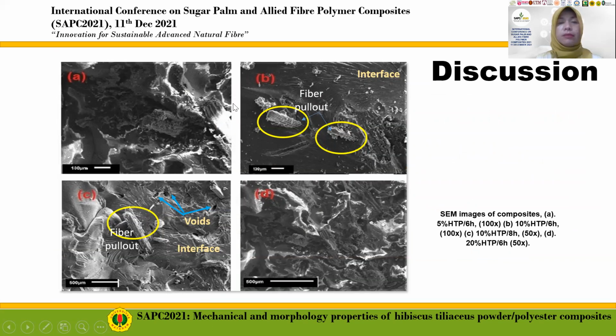Ladies and gentlemen, as you can see in figures A, C, and D, we know that the interface bond between the powder and matrix is not dense. The hibiscus pull out and fracture occur along the matrix or resin in the composite, resulting in low mechanical strength.